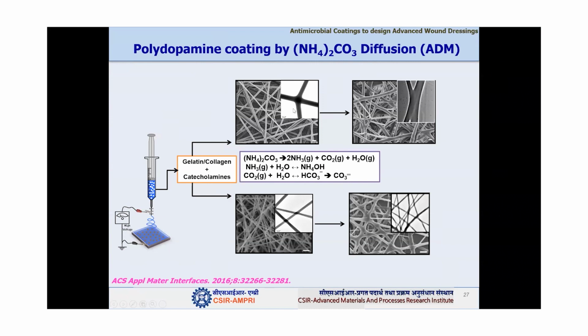So what happened when we put these dopamine-rich nanofiber mats into this chamber? You can see here the dopamine inside the fibers got polymerized, and this cross-linked morphology we have attained. This is gelatin nanofibers with polydopamine. You can see the fiber diameter also increased, and you can see the complete merging of these nanofibers. They actually merged at the junction.